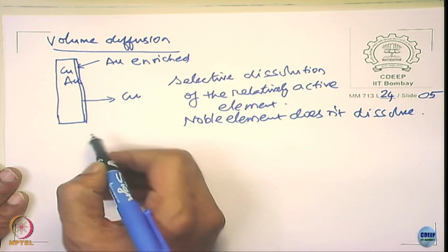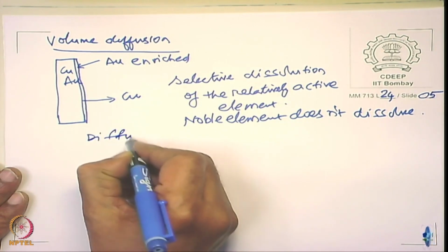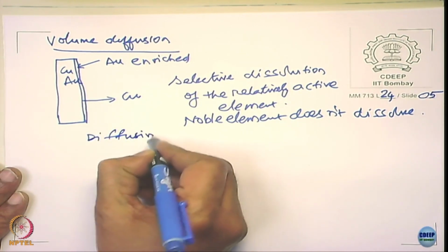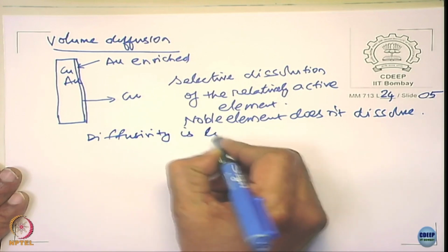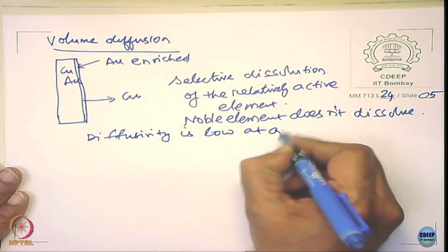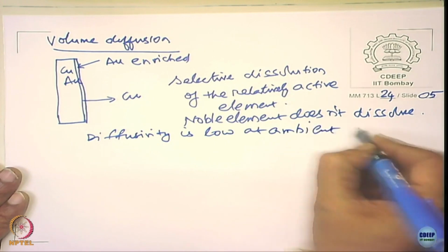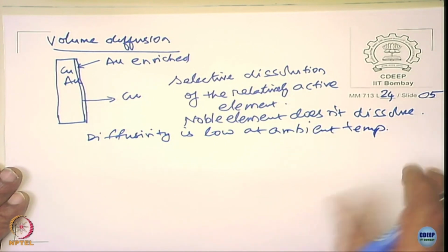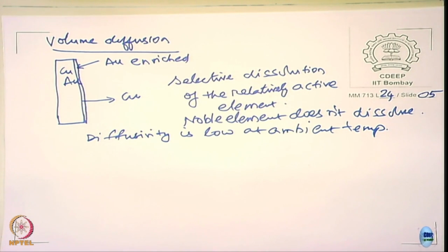because the diffusivity is low at ambient temperatures. You might have heard of high temperature oxidation, right? There you talk about diffusion of aluminum, diffusion of chromium to the surface, diffusion of silicon to the surface, get oxidized, forms a nice protective film and all possible. But at ambient temperature, the diffusion of these elements is so low, you do not expect them to continue with the dissolution process.